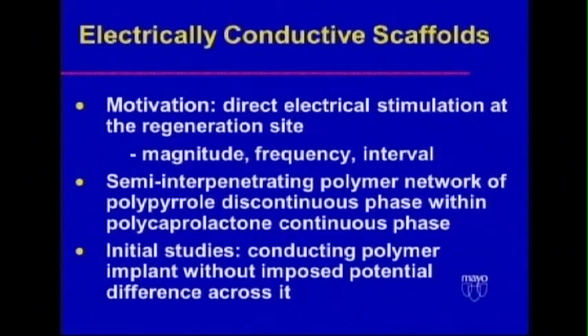Really was pretty nice. So then I thought, okay, if charged surface works, how about conducting? Nerves conduct electricity. I asked Brett Runge, a PhD in our lab, to see if you can make a nerve tube that conducts electricity. And I said maybe an IPN would work, an interpenetrating polymer network. We looked at a number of conducting polymers. He chose polypyrrole, which, as those of you who've worked with it know, is black. Everything is black when you make something with polypyrrole. But Brett found that if we made the tube the way we always made it, a porous tube, one of the chemical initiators for pyrrole polymerization would wet the internal surfaces of the pores.